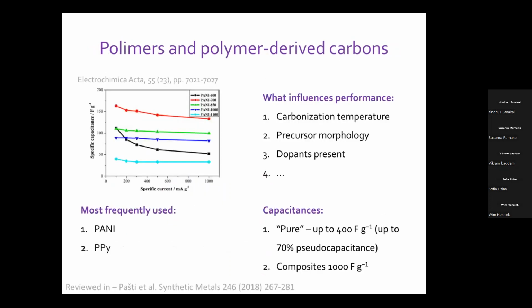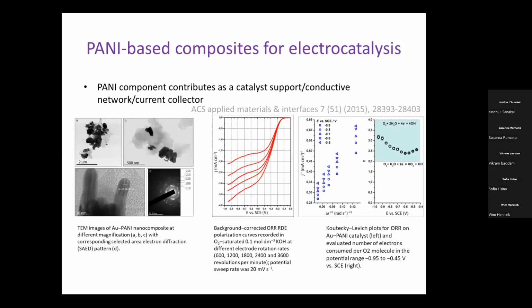Overall, these polymers and polymer-derived carbons have interesting properties. A lot of experimental conditions influence their performance, and we have capacitances up to 400 F per gram for carbons, but for composites, we can get even 1,000 F per gram. Then we can focus on electrocatalysis, and composites of conductive polymers are really interesting. And this is an example of a PANI gold composite. At that point, it sounded like a good idea because gold was cheaper than platinum. The situation is now different. But we can see that in principle, it works even in alkaline media, where PANI should not behave the best in principle.